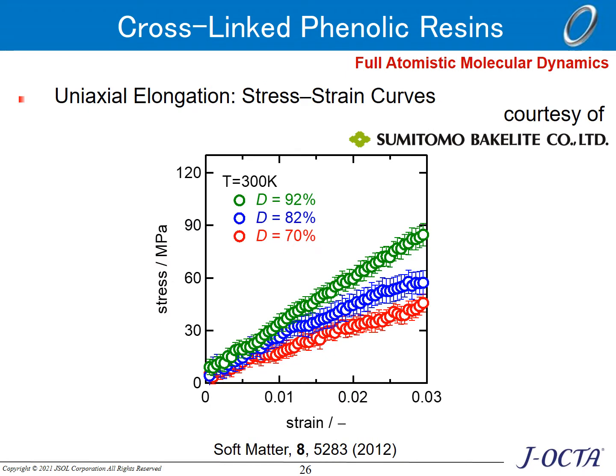The stress-strain characteristics are evaluated by applying uniaxial elongation to the structure. In the graph, red, blue and green represent the results for the cross-linking ratio, 70%, 80% and 90% respectively. The slope of the graph represents the Young's modulus. The increase of Young's modulus by the degree of cross-linking can be confirmed using molecular simulation.